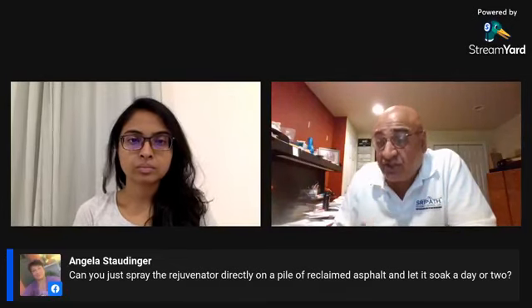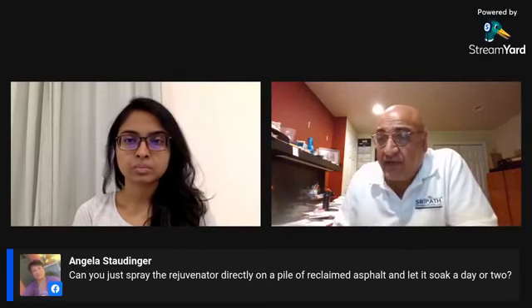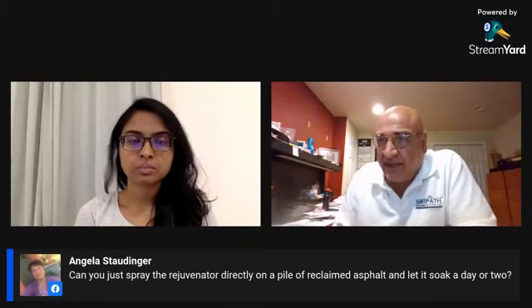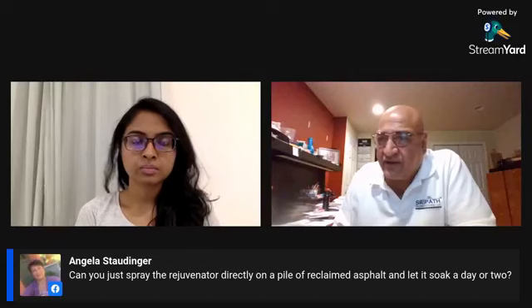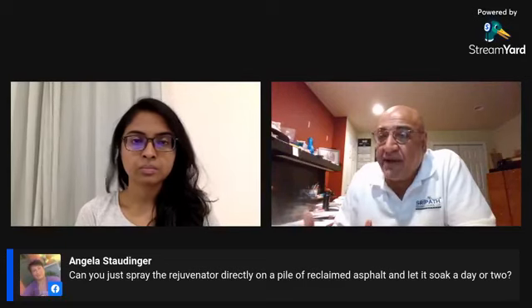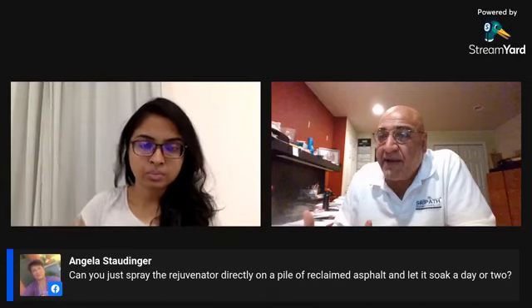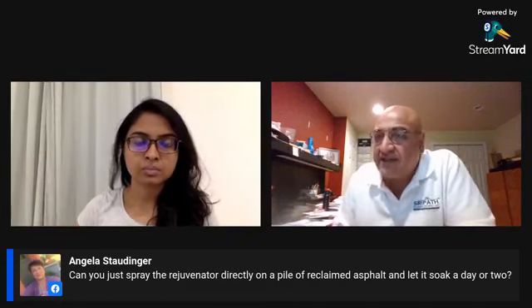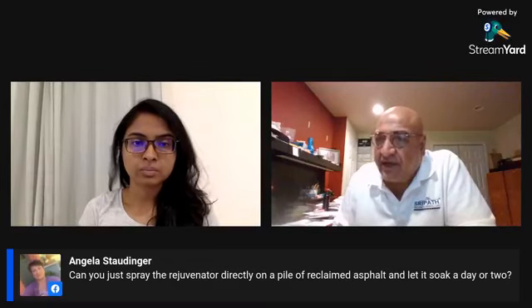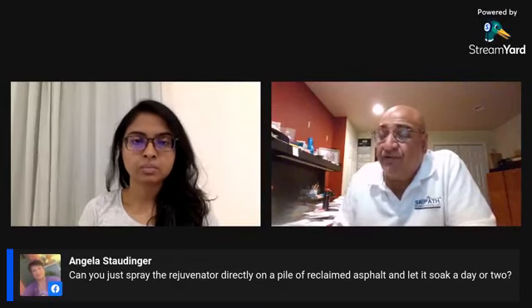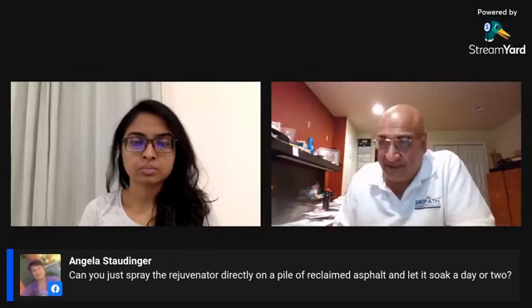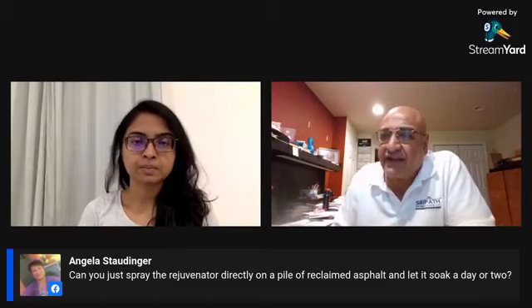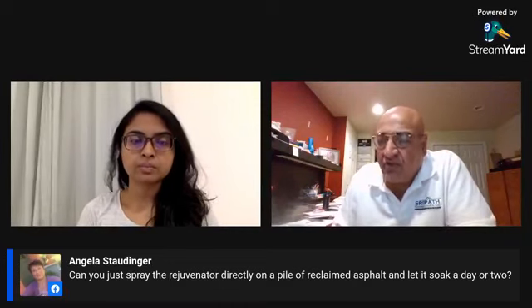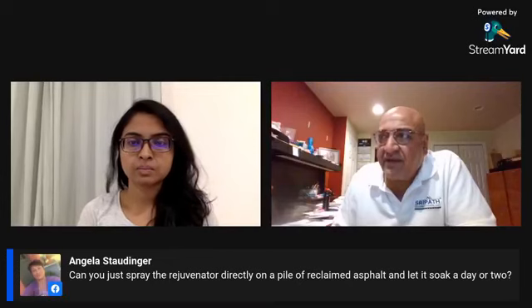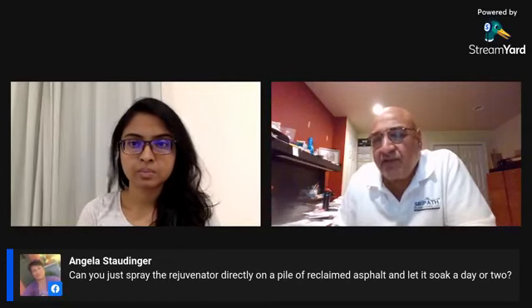And we have studies that show that if after making your mix you lead it typically to a storage silo, or you lead it directly to a truck, if the residence time in there is anything greater than 20 minutes, then you're good. The diffusivity rejuvenates the mix. Even when you add it to the virgin binder and you introduce it like that, it gives you a fully functional mix within about 20 minutes. And that is more than enough for even the fastest operations around the world. And so from a practical standpoint, it's not advisable to add it to a RAP pile.